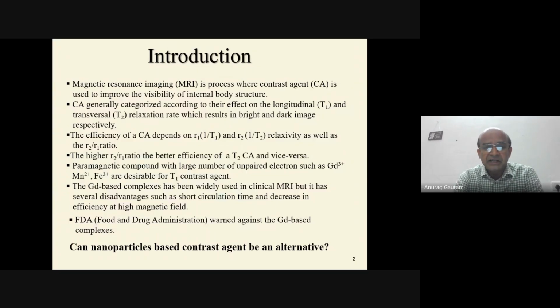Then a third parameter: each contrast agent, whatever contrast we see, has both T1 and T2. If you put any material in water, it will relax both ways, T1 and T2. But one is higher, either T1 or T2, depending on the nature of the material, whether it is paramagnetic or highly magnetic. For gadolinium, the one currently used at clinical level, it is a T1 based contrast agent. For the tumor, it produces whitening contrast compared to the normal tissue, whereas dysprosium produces darkening contrast.